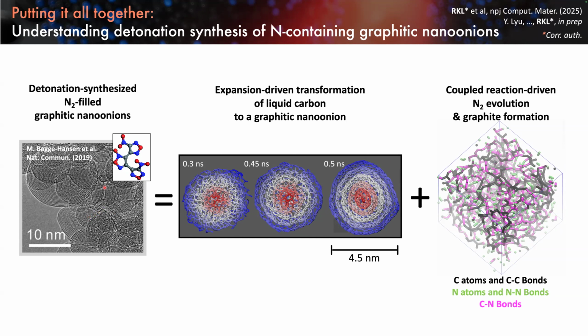They recently took these particles and did more analysis using the TEM electron beam to pop the particles while taking their chemical spectrum. They found that the triple bond character and nitrogen signal dropped off when popped, which is consistent with molecular nitrogen evaporating out of those particles, matching our simulation predictions. So we can use these simulations to guide strategies for designing materials and to help interpret how complex particles like these form under shock and detonation conditions.